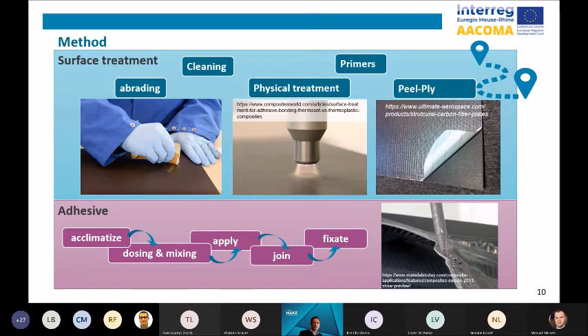At last, a surface treatment unique for a composite is to make use of a so-called peel ply. With a peel ply, the last top fiber layer is embedded in the matrix, and this layer can be torn off just before bonding. This creates directly a fresh and clean bonding surface, and further treatment may be necessary afterwards, but you start with no contamination from the outside.